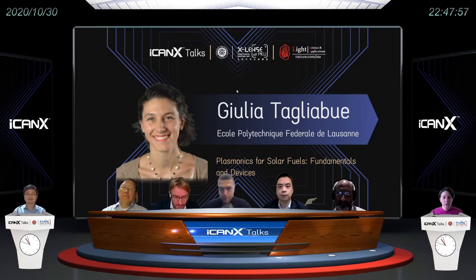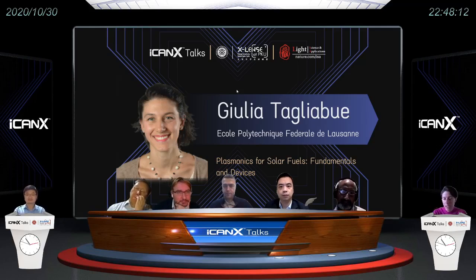Yes. So for the reduction efficiency, there are a lot of strategies which are similar to those of hydrogen, especially in improving the photonic aspects of the electrodes, maximizing the absorption and the charge generation. If you have a semiconducting electrode, obviously the balance between surface area and charge recombination is very important. I think for the CO2 reduction, as I mentioned at the beginning, the real major challenge is more than the overall efficiency at the moment.